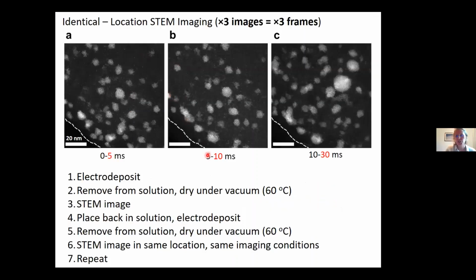Okay, so just to remind you, in this experiment, this is what we do. We deposit for 5 milliseconds, we take out, we image, we put back in for a further 5 milliseconds, we take out, we image, we put back in for a further 20 milliseconds. So we have time stamping at 5 milliseconds, 10 milliseconds, and 30 milliseconds of the process, and we're looking in exactly the same area. Now, obviously, one of the things we've had to work really hard on is bringing the substrate in and out of solution, as anybody doing identical location work must, and not getting perturbation of the particles or whatever's on the surface due to how we've handled it. So handling is essential, but handling is essential anyway for anybody doing any form of microscopy.